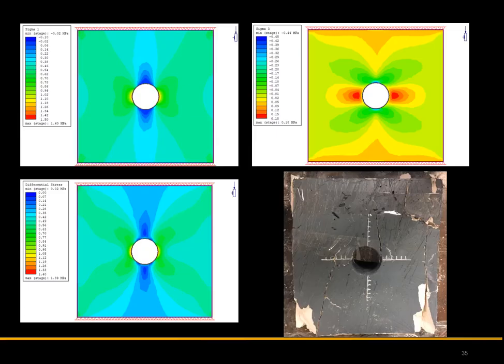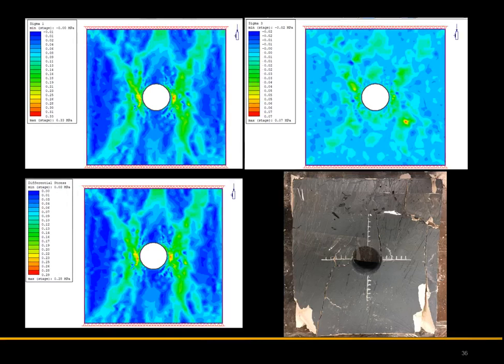These calculated values were then reapplied to the numerical model, and it can be seen that the deviatoric stresses compare well to how the test block actually failed. As a point of interest, the model was changed from elastic to elasto-plastic using the Hoek-Brown criterion. Other works note that brittle rock does not follow a standard failure curve; however, the stresses in the elasto-plastic model resemble the failure lines in the test block, which is interesting to consider.